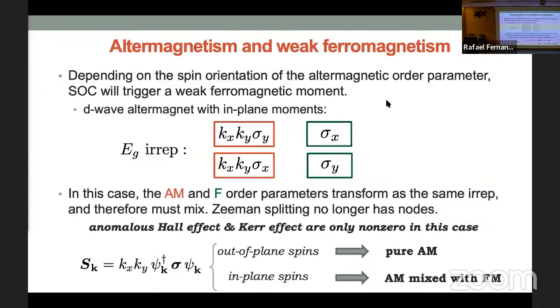And here's now the other side of it. I chose my moment to be out of the plane. What happens if I choose it in the plane? Well, in this case, it transforms as the Eg irreducible representation, but that's exactly what a ferromagnetic moment is. So you see in this case here, if the moments point in the plane, I'm going to induce weak ferromagnetism. So in this case here, out of plane spins is a pure altermagnet, in plane spins mixed with ferromagnet.